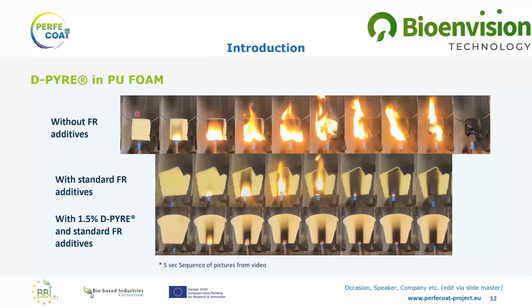Here I give an example of D-PYRE, which is the flame retardant, used in a polyurethane foam. The top row of pictures that you see here are a foam that is fire tested without any fire retardant additives. And as you can see, it burns completely. The second row shows pictures where the foam has a standard fire retardant additive, and you see that it burns less and retains its structure. The last row here is with 1.5 PHR D-PYRE plus standard fire retardant additives. And as you can see, the flame height is even lower than with the standard fire retardant, and also the structure is better preserved.